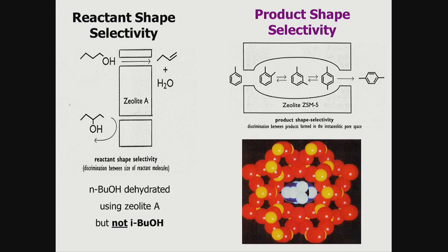The one at the top is just showing you that you can be para-selective. Paraxylene is produced if you take a disproportionation of toluene. That means you lose one and it gives you benzene, and you gain two and you get orthoxylene, metaxylene, and paraxylene, which are the structures inside the zeolite. Trouble is, that slide misleads you. Basically, what happens is the structure is limited and the diffusion out is so slow for the two on the left that only paraxylene comes out. And we've looked at that before. I put that on the board the other week and gave you a little diagram.